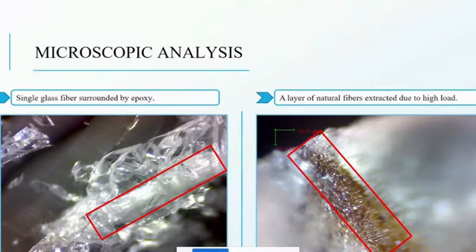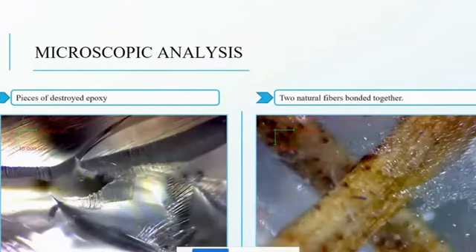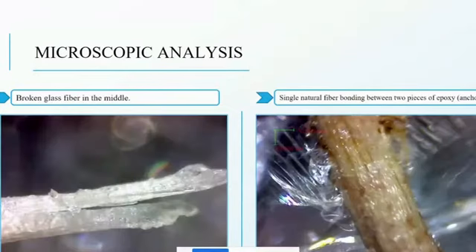This is a single natural fiber, or palm tree fiber, in the epoxy during the fracture, but it is internal, inside the sample. Here is just the epoxy, to see the fracture, which is brittle, and we can tell from this picture how it looks. We liked this picture, so we added it: two natural fibers bonded together with the epoxy. Finally, this is a broken glass fiber in the middle. It's like a bundle, and there's a fracture here that we got from the small punch test after testing. And finally, this is a natural fiber bonding between two pieces, or anchoring inside the epoxy after testing.